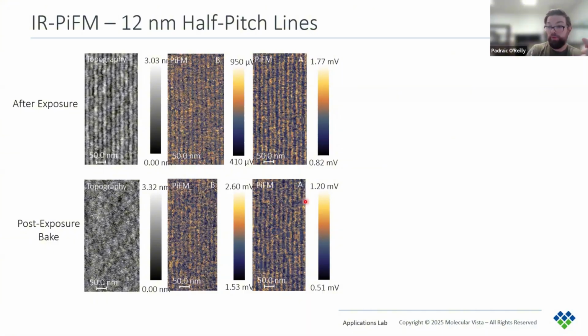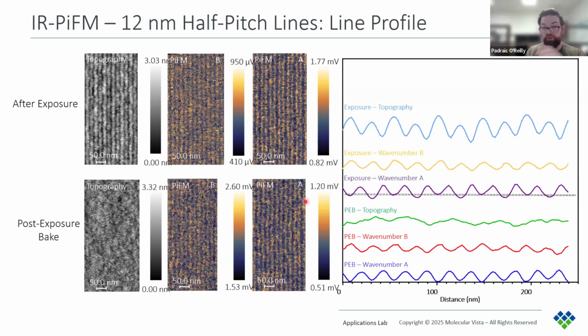Now, when we look at the line profiles across these, we can see some interesting things that might not have been immediately obvious. These line profiles were averaged down the entire length of the images, and there are two things that I want you to focus on. As I briefly mentioned previously, the green line here shows the post-exposure baked topography. Again, it doesn't show obvious topographical patterns, but the chemical maps do. This is for the red and blue lines. And so PiFM can detect something that standard AFM cannot.